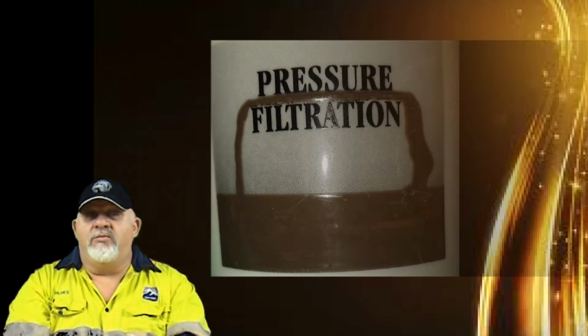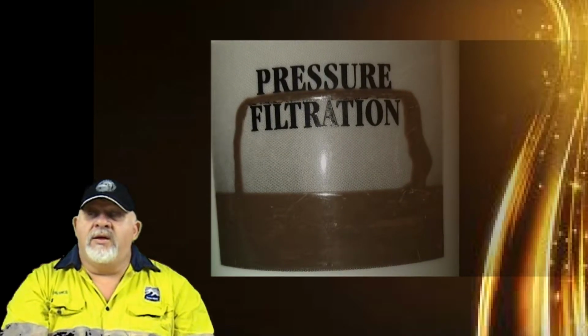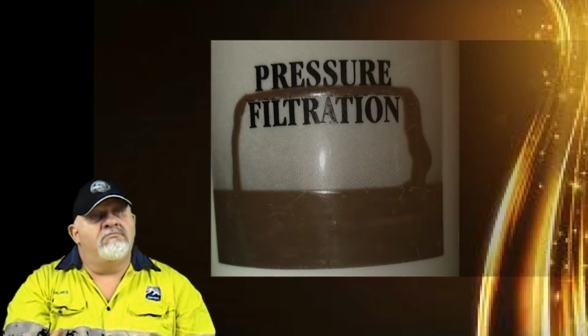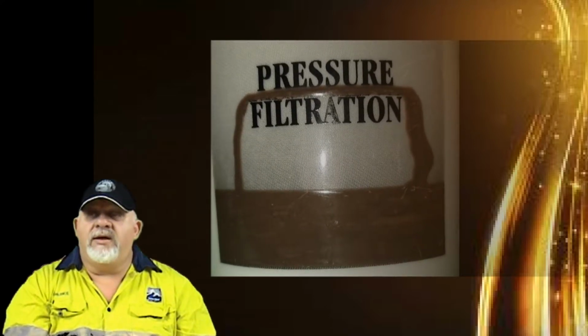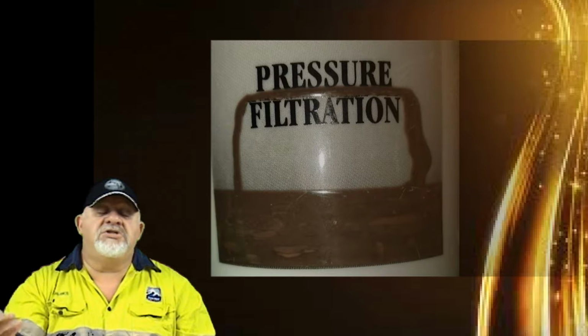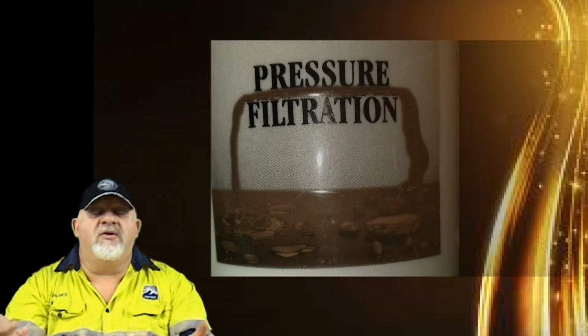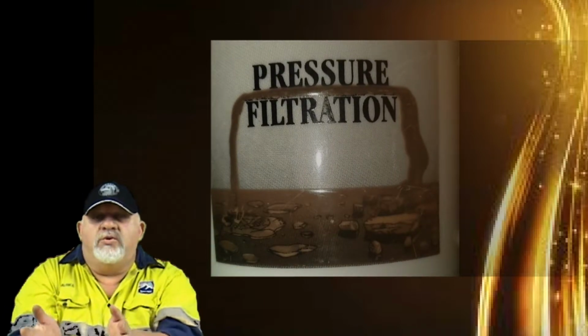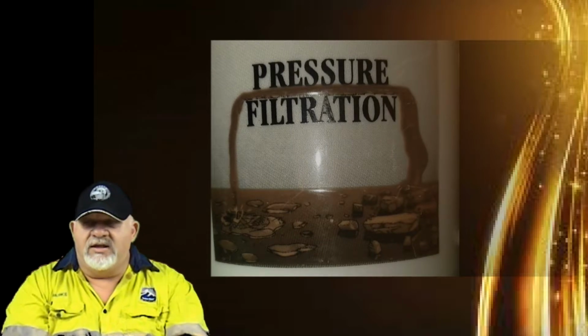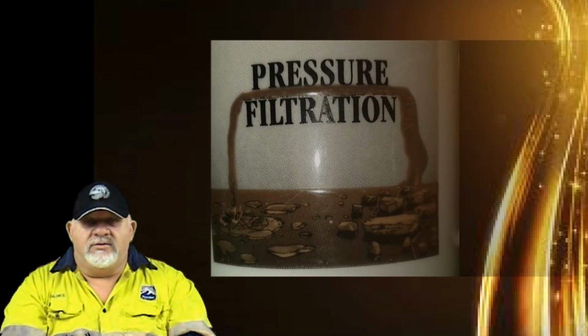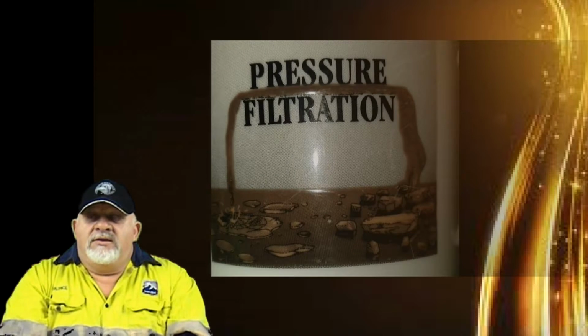That filter then removes the water from that, and we have not a dry concentrate, but a product which generally is between 7 and 9% moisture, which is a good moisture for transport. It keeps everything together and doesn't create dust and all that sort of stuff. So then that goes off to the customers who are chasing it.